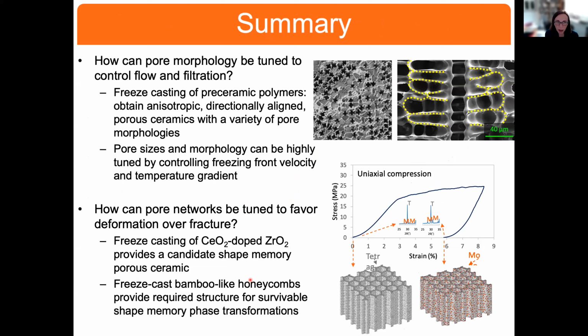So to finish off my presentation today, I hope I've given you a sense of what directional freeze casting can produce. And also that in terms of the 2 applications, we can produce these highly anisotropic structures, different pore morphologies, and they can be tuned to provide good separators in flow and filtration. And secondly, albeit very quickly, we've looked at these ceria-doped zirconia structures as candidate shape memory applications, and can produce a bamboo structure that is going to be robust in contrast to denser bulk materials, and survivable then in shape memory applications.